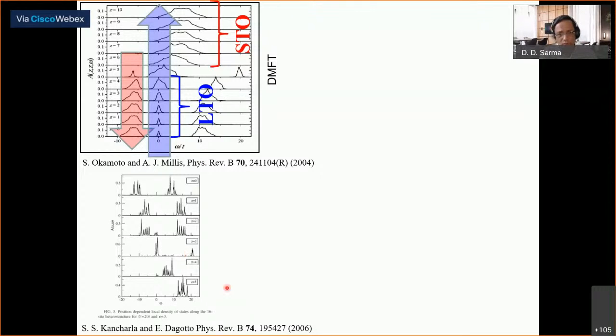Whereas if you look at this one coming from Dagotto's group, here the interface layer is here, and you can see the changes are very quickly over. This is the chemical potential, there is electron density at the interface layer, and that electron density dies out very quickly, unlike in this particular description. And here the Mott-Hubbard peak remains at exactly the same energy, but here it changes its energy. And this part, of course, we'll not see, let's not talk about that. So in this case, it is almost entirely tied to the interface layer. Here it changes over many layers. Here the Mott-Hubbard peak changes its intensity over many layers.